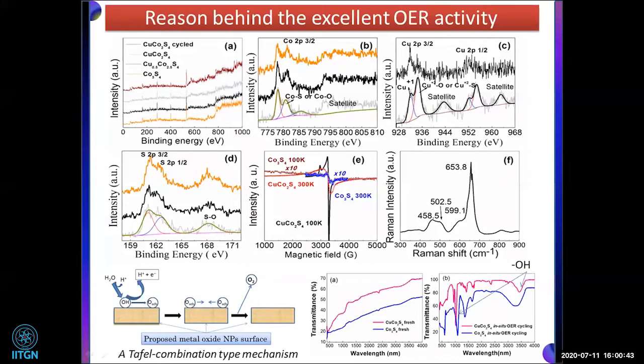In the XPS you can see here the cobalt 2p spin orbit doublets and shake-up satellites, which give the cobalt 2p3/2 and cobalt 2p1/2. There are cobalt 2 plus and cobalt 3 plus, but the cobalt 3 plus intensity is more, which shows that there is more cobalt 3 plus than cobalt 2 plus. Then in case of copper, there are peaks for both copper 1 plus and copper 2 plus. And the copper 2 plus gives a stronger copper sulfide bond, and it shows that a higher ligand to metal charge transfer occurs in this one.